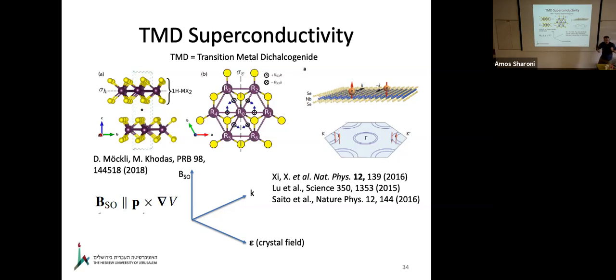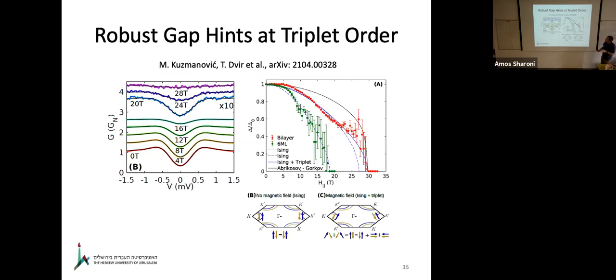And that's a very good thing, because that means you can apply a very high in-plane magnetic field and not destroy the superconductor. That's been shown using transport measurements. My group has been doing this for some time, trying to build tunneling devices into this material, taking such a device to Grenoble, measuring up to 30 Tesla, and we are arguing between ourselves and with the referees of papers: why does the gap survive into such a high magnetic field?